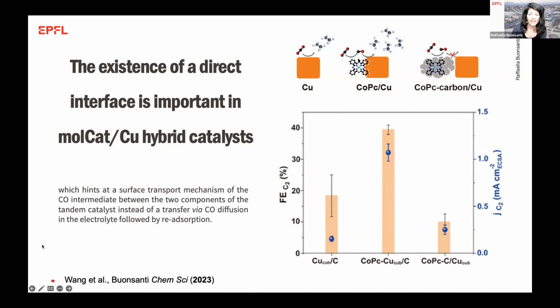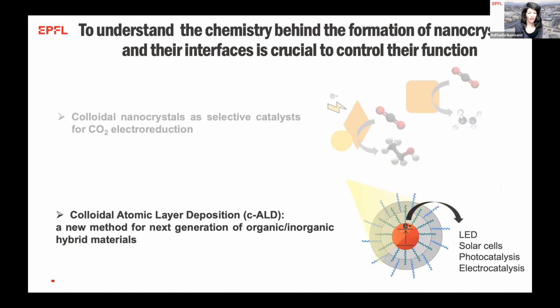the copper. And this indicates that, again, there is a synergistic interaction and a direct transfer of the CO from the molecular catalyst to the copper cubes, rather than diffusion of the CO in the electrolyte. So again, the importance of an actual interface between the two components. And we will continue now our journey into interfaces by looking more at the surface chemistry of nanocrystals with this colloidal atomic layer deposition.